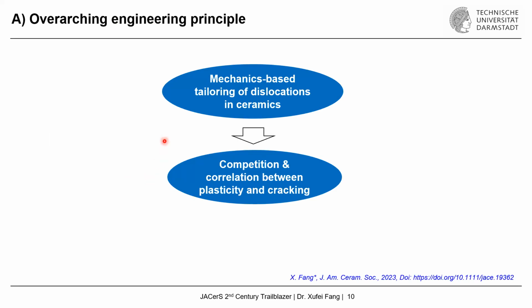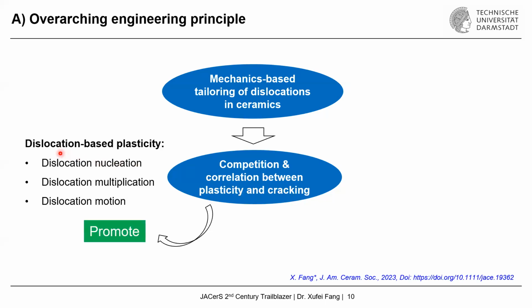So when we look at the mechanical deformation of ceramics, in comparison to metals, we need to pay attention to, besides the possible plastic deformation, also the crack formation, which is more prone to happen in ceramics because they are usually considered brittle. So that means we need to look at the competition between the plastic deformation and crack formation. And in the specific case of dislocation-based plasticity, we would like to break it down into dislocation nucleation, multiplication, and motion. By nucleation, that means generating dislocations from 0 to 1.